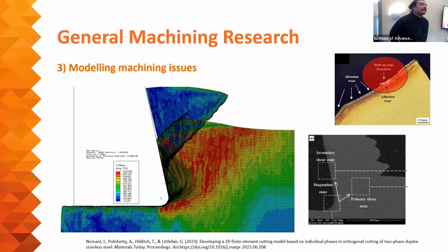But yeah, we managed to get good correlation in terms of von Mises stresses and strains to what we observed experimentally, and also the shape of the chip which was generated from the model. We were able to get good correlation between virtual and experimental data.